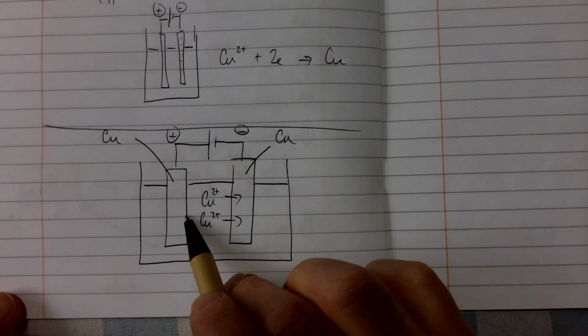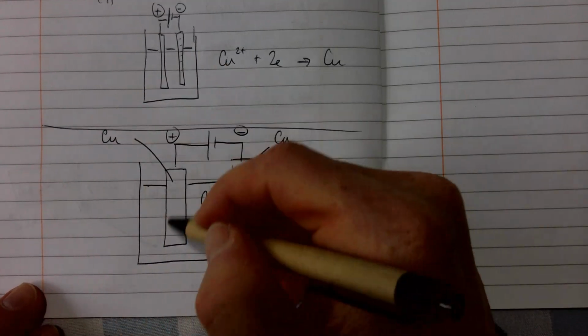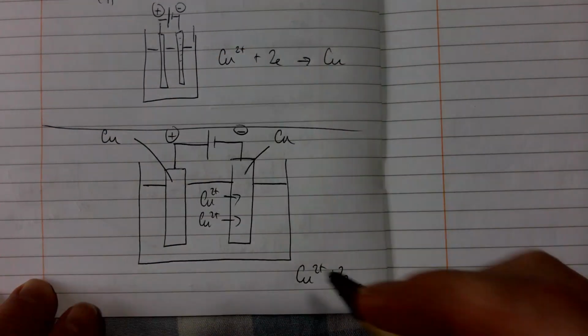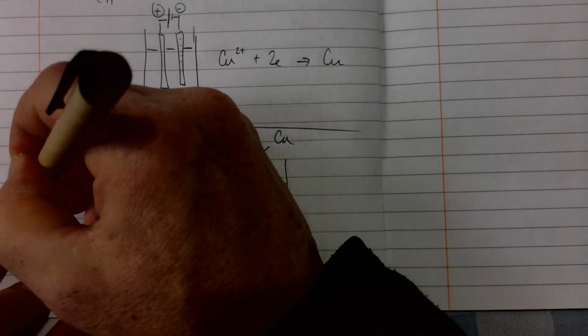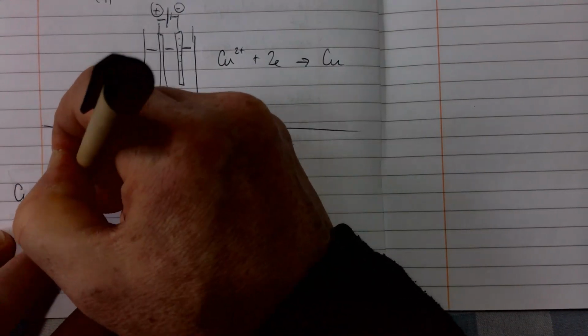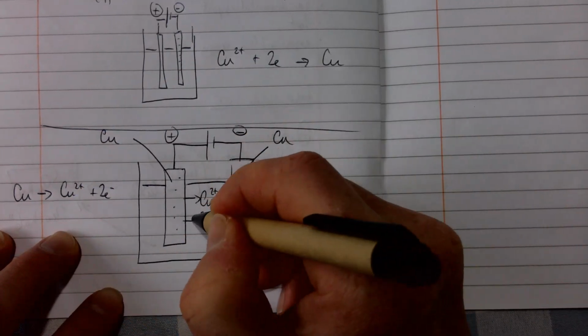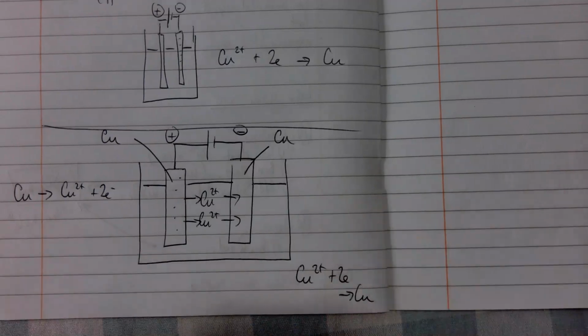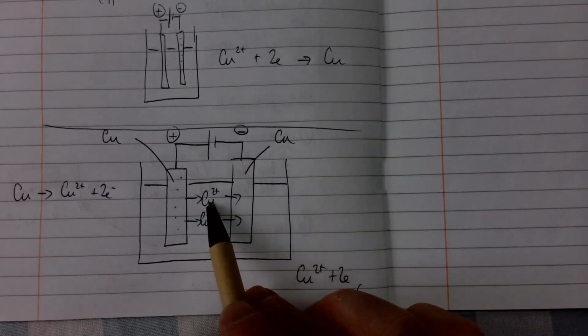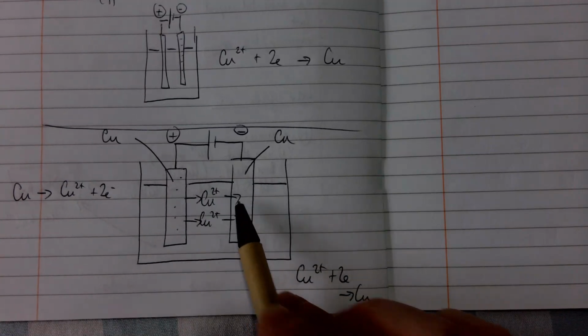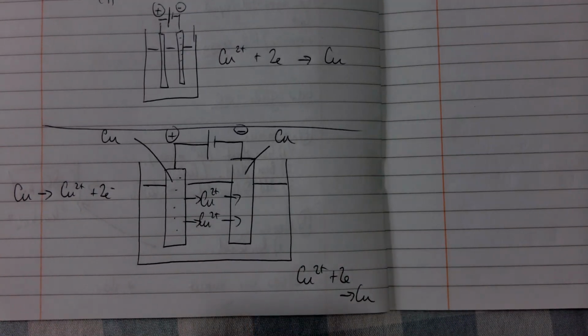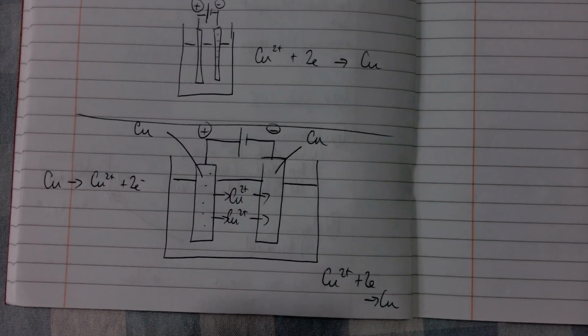But over here, the impure copper, which is actually the electrode now rather than carbon, and which may have all sorts of other impurities in there, is turning into copper ions. They get oxidized to copper ions, which travel across and then reduce to copper atoms again. So you can use electrolysis to purify copper too. There's a little bit in the textbook if you want to read up on it on your return.